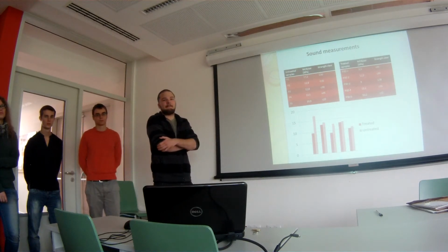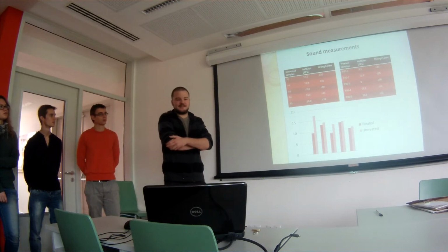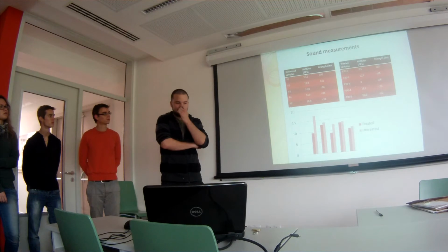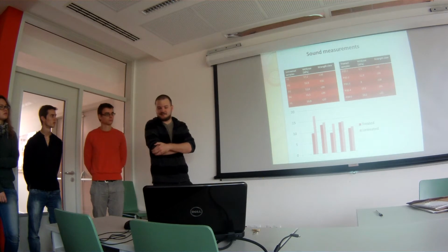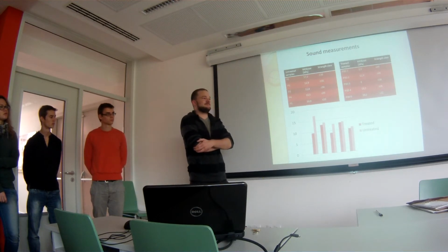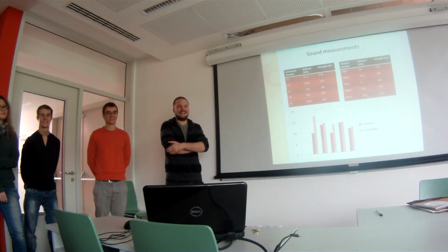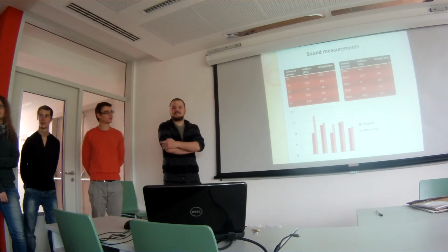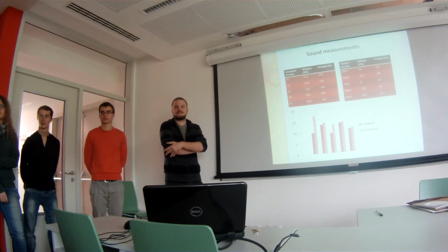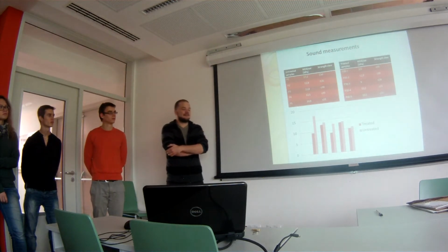But maybe I'm going too much into theory. How did you get those numbers, by the way? I was wondering about that. Well, we had an equation that the instructor gave us, and I think he has enough experience that I can believe him. You should question everyone. There is the European standard where you can check what modulus of elasticity matches which strength class. So you could just read it based on the modulus of elasticity.